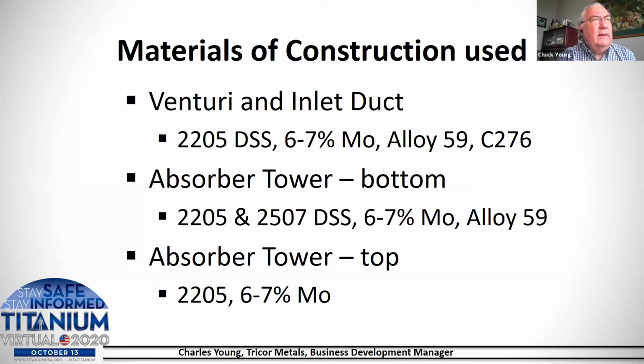The upper part of the tower going into the stack has to be an alloy, but it does not have to have too much corrosion resistance because the temperature is lower, and you probably don't have too much sulfur going up there, so the pH is probably not critical. The other part of the scrubber, and we'll get into that in a second, can be other materials.